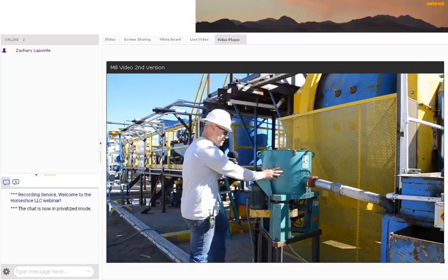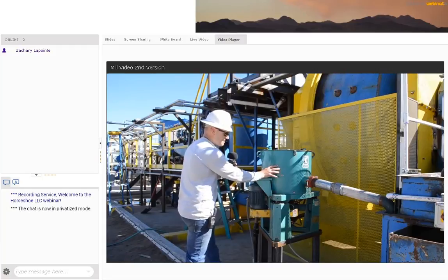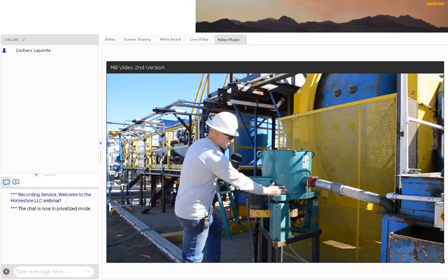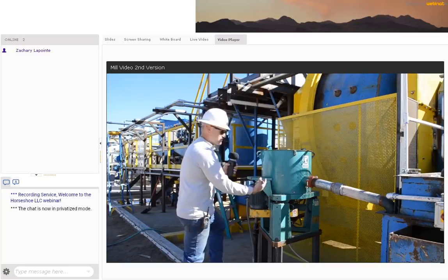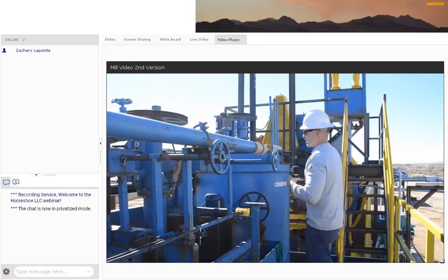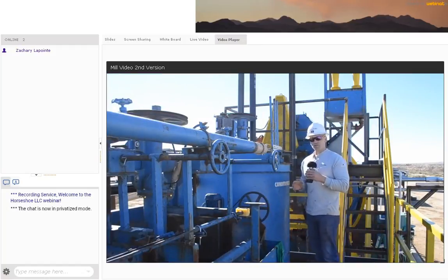The Knelson concentrator is by far the most important piece in processing our ore. When we opt to feed slurry from the cyclone to the Knelson concentrator, the ore is fed into the cylindrical chamber with a ribbed sleeve which spins and separates heavies, free gold. Once the entirety of our ore solution has passed through the Knelson concentrator and we have extracted all of the free gold, we then pass our solution on to the float bath system.